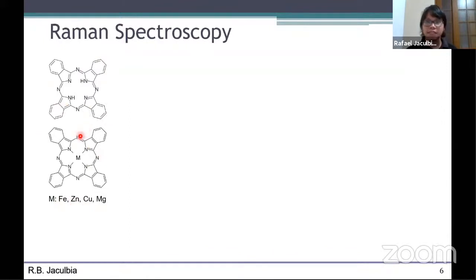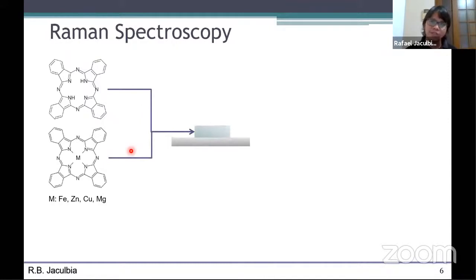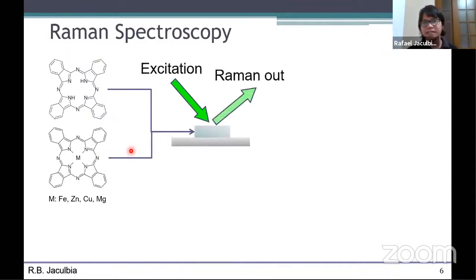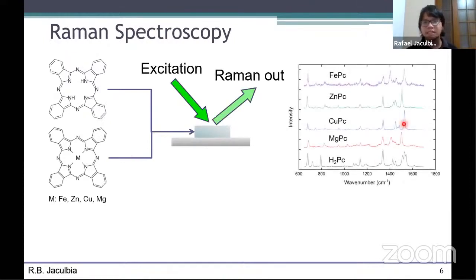Now, if you see this, they basically look the same to us, especially to physicists. But when you want to see what molecule this is, you can do Raman. Just put this molecule on the sample plate, then shine light and detect the Raman signal. And in fact, you will see that these molecules have very different Raman spectrum. Since each of these Raman modes represents a particular vibration, there can be common Raman modes between these two molecules because they are structurally the same. But as you can see here, the intensities are different and there are slight shifts of the Raman signals. With this information, you can identify each of them, based on the spectrum alone.